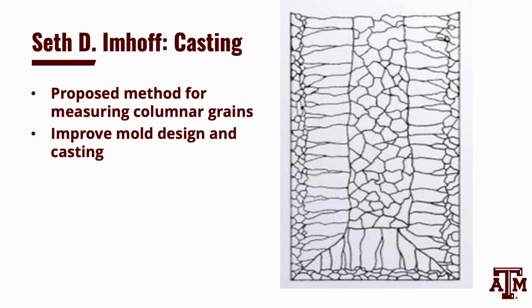In addition, I read a paper by Seth Imhoff called Field Casting Support and Microstructural Feature Examination. Imhoff et al. found a way to measure columnar grain structures in a cast. A cast generally contains columnar grains in the mold wall. It is hard to measure columnar grains because they are elongated and perpendicular to the mold wall. This method will be shown in the next few slides, and I will show you how it is used in the cast microstructure to measure those grains based on the nucleation sites.